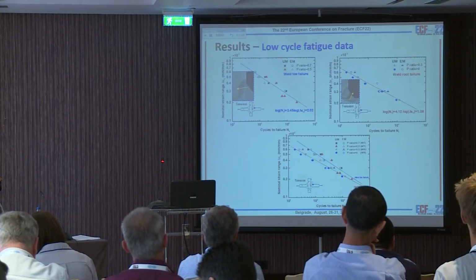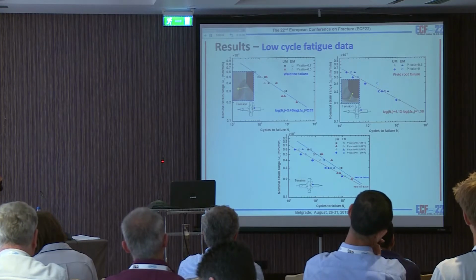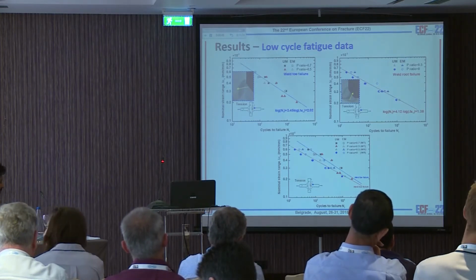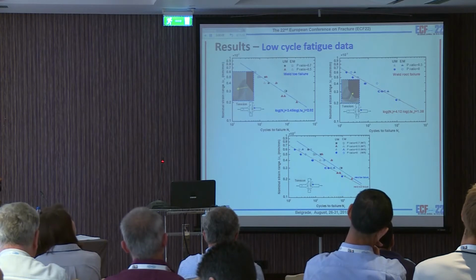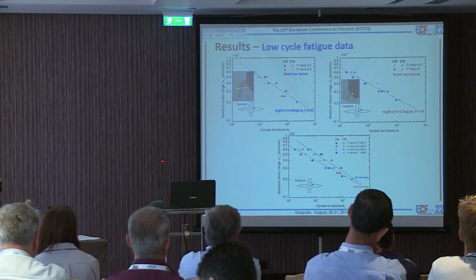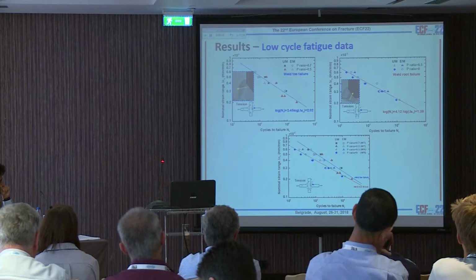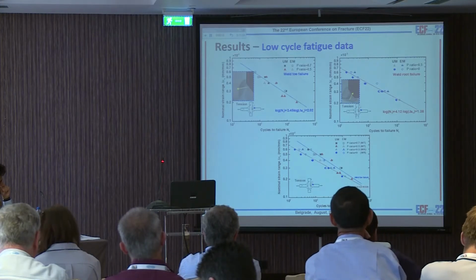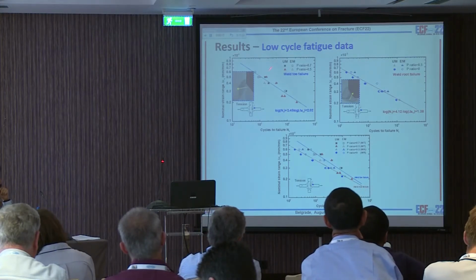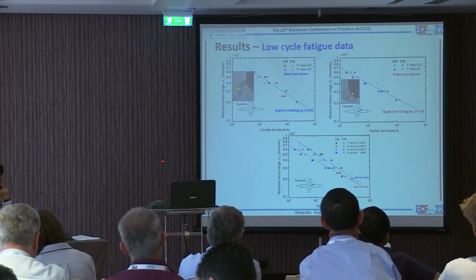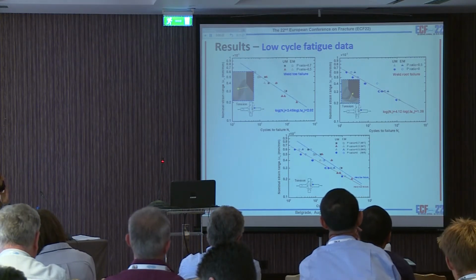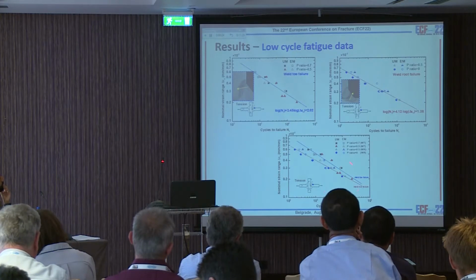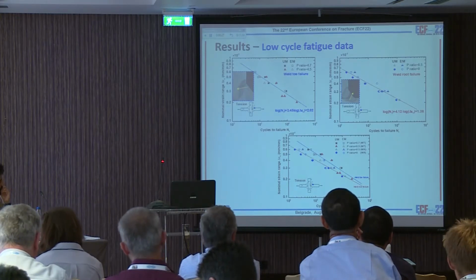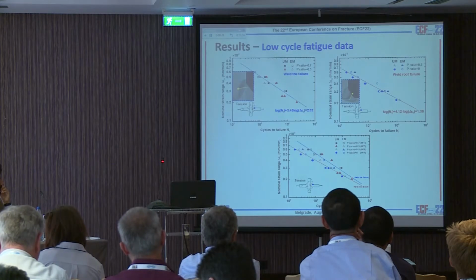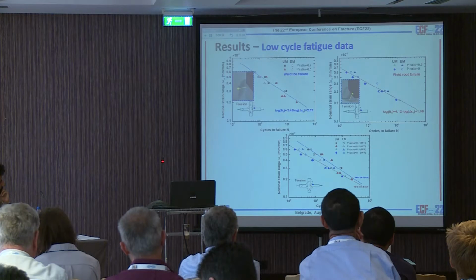So this result is about the low cycle fatigue data, and we fit using the linear relationship about the welded toe failure and the welded root failure, and finally we compared the results between the welded toe failure and the welded root failure.